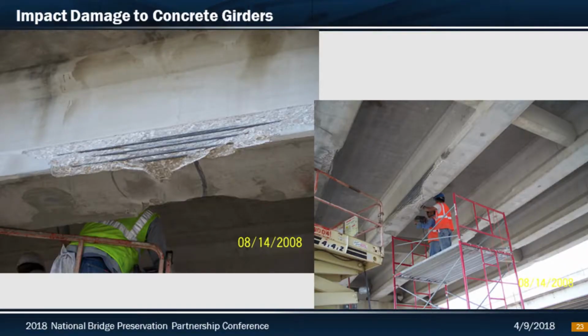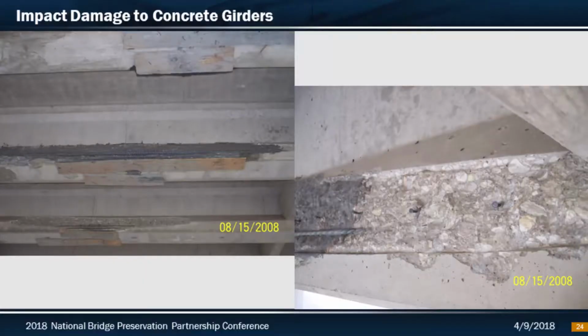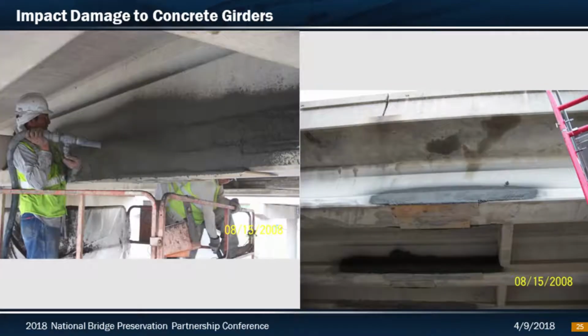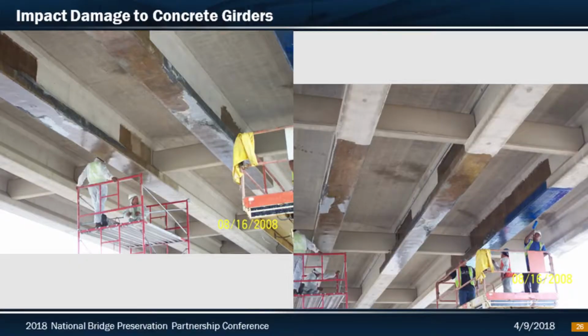This was on IH-20 in 2008, another pretty severe hit. We just did some small splicing, formed it up, and patched our concrete. There's a pneumatic placement. Again, the pre-saturation is mentioned, and we have to have our surface prep proper. CSP 2 or 3 was mentioned again, which is an abrasive blast.